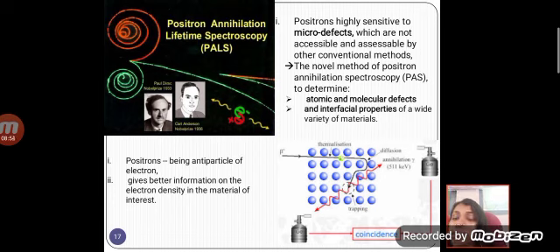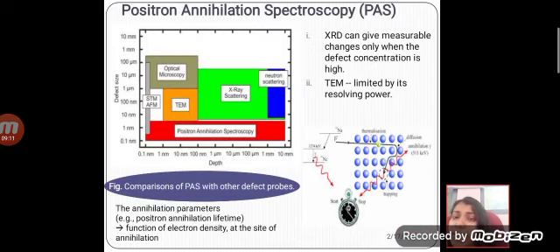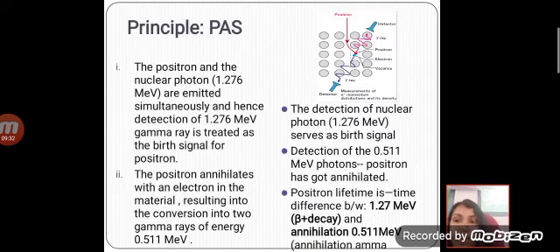Now moving to the wonderful and fascinating positron annihilation lifetime spectroscopy. Positrons, being antiparticles of electrons, give information on electron density within the material. So this is used to determine the atomic and molecular defects within the materials. While XRD can give measurable information only when defect concentration is high, and TEM is limited by its resolving power, positron annihilation spectroscopy can detect defects even when the defect concentration is very low. So this is the advantage of using positron annihilation spectroscopy. And we have done these experiments at Saha Institute of Nuclear Physics, Kolkata.